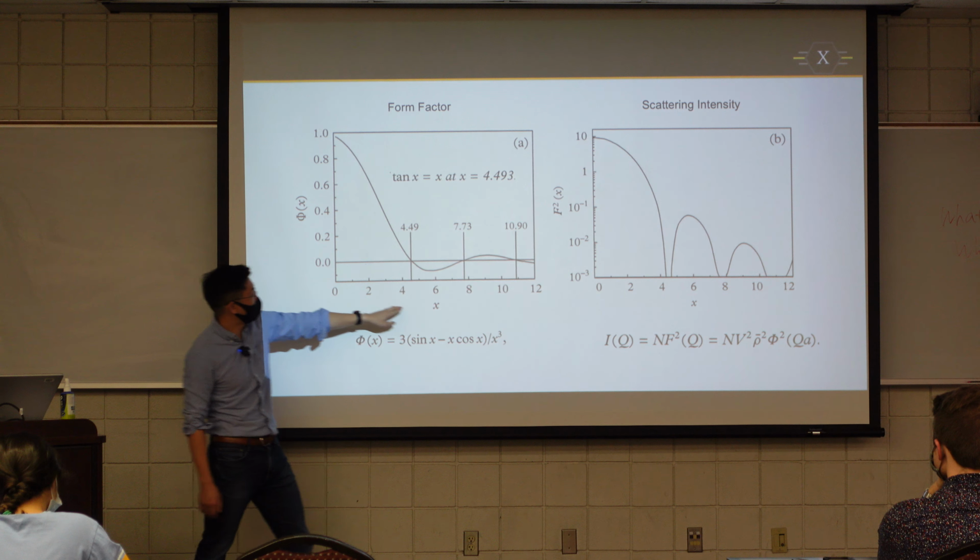Come on, you guys did a good job with Q. It's like your structural information in inverse space. Yeah, inverse space. That's what I want to hear. So Q is inverse to the size. You can use 2 pi divided by Q to visualize a ruler of what we are looking at, or if you want it simple, just use 1 over Q for a quick reference of the size we are looking at. If you use 1 divided by this value, it is roughly about 100 nanometers, and if you multiply by 2 pi, this roughly translates to a real space of 600 nanometers.